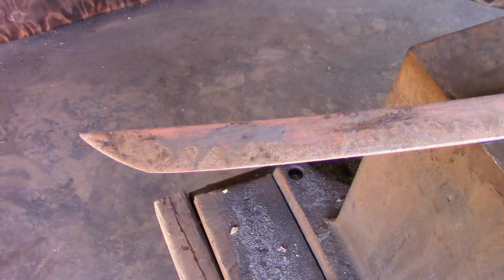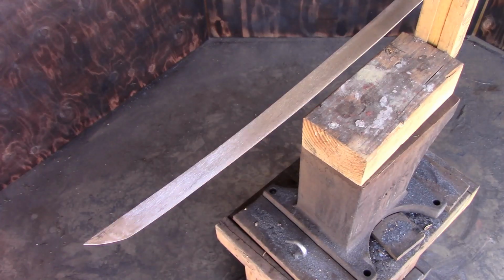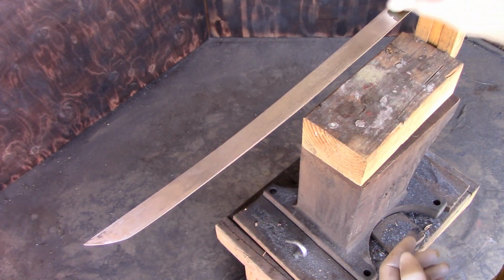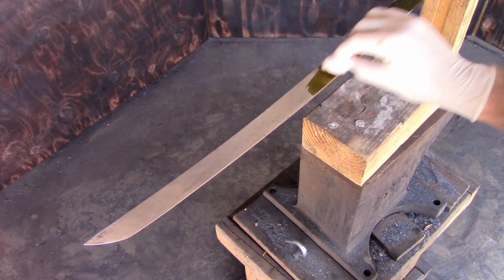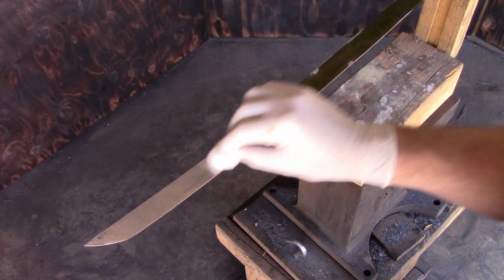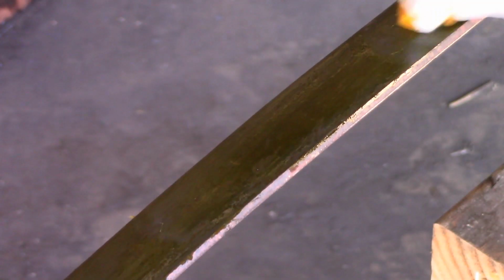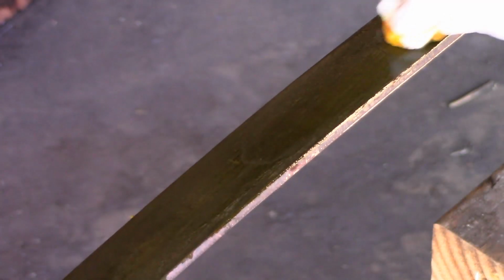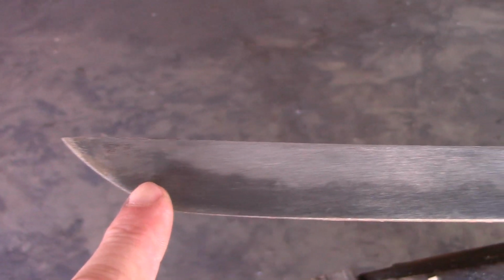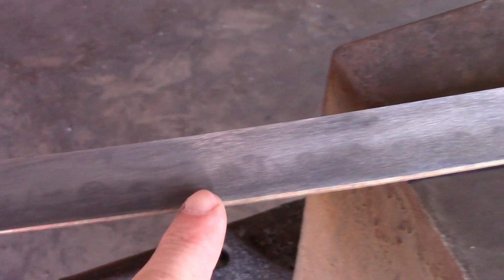Even at this stage, you can tell by color differences in the metal that the hamon is going to be good. But if any doubt remains, there's a simple method to reveal the quality of the hamon before beginning the polishing process. You can quickly sand the blade with 120 grit sandpaper and then etch it with ferric chloride. If the quench was a success, the cutting edge and spine edge etched differently, with the cutting edge coming out a darker shade of gray. It's easy to see that this hamon is going to be quite dramatic, active, and beautiful.